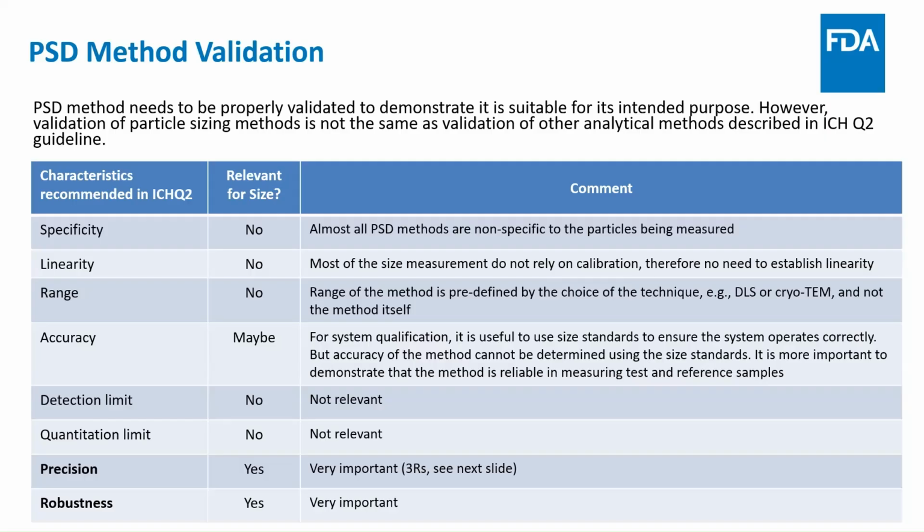The measurement relies on mathematical equations and on the sensor reporting out some data, and using that data, putting it into the equations to perform a calculation. And the calculation does not take into account any other information other than what you put into the software. So in a way, you do not need to calibrate it. So there's no range of the size being valid or linear response to size.